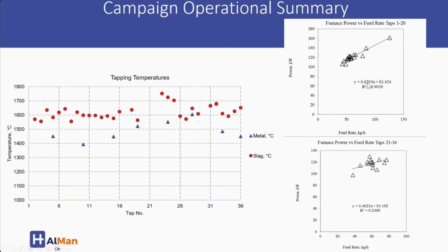The preliminary simulation estimated 0.5, and the reason for this difference is because we had to add much more aluminium than what was initially simulated. A similar thing with the pre-reduced ore: actual measurements during the test work gave us an SCR of 0.4, while the simulation gave us an estimated 0.2. Again, the simulation estimated that we'd need much less aluminium, but at pallet scale, at a larger scale, the efficiencies are not so great, so we had to add much more aluminium, meaning more energy will be required.